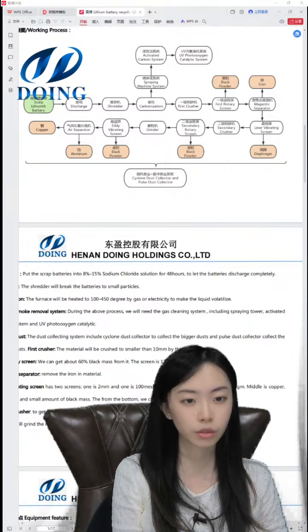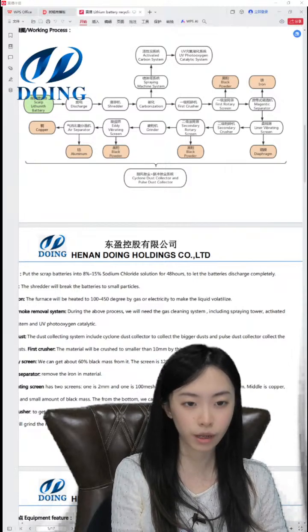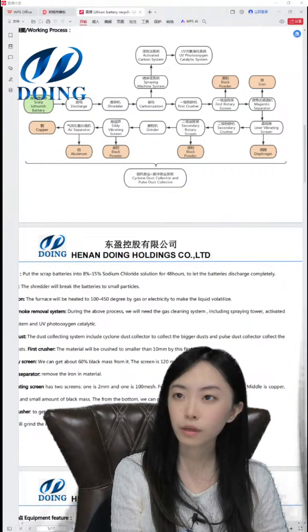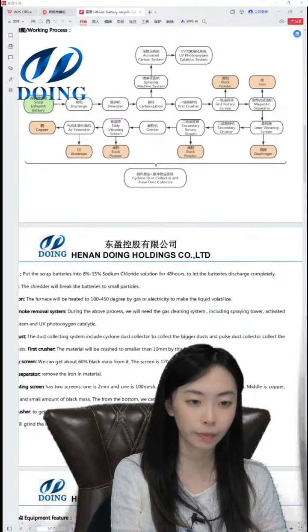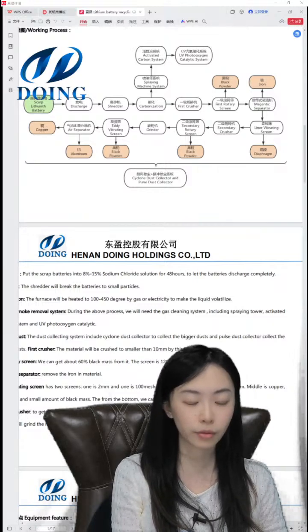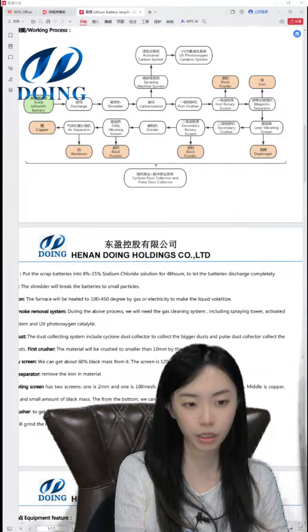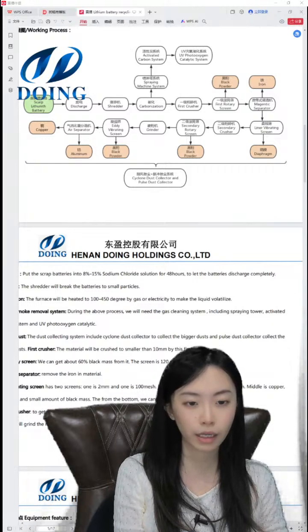Then it will come to the additive vibrating screen. Here the additive vibrating screen will collect most of the black powder. It is a high-precision screening machine with low noise, high efficiency, and a well-sealed structure, so it's applicable to granular and powdery materials. The recycling rate of the black powder is about 99% in this process.